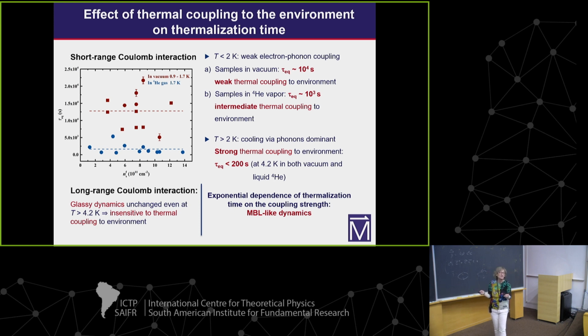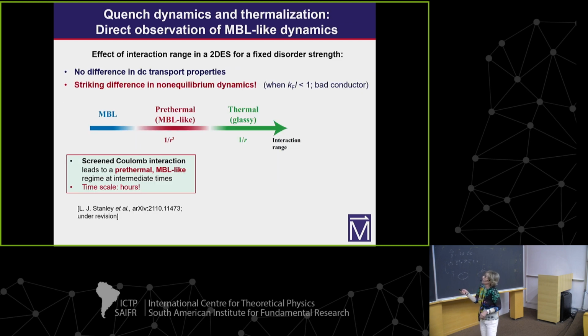In fact, it is this sensitivity to the coupling to the thermal bath that has been suggested to be used as a key experimental signature, or a way to distinguish between glassy and MBL-like dynamics. So this is what we have found: in the long-range case, the system thermalizes, but the dynamics is glassy because the system is frustrated. We have disorder, we have long-range Coulomb interaction. In the dipolar case, the dynamics seems to be consistent with pre-thermal MBL or MBL-like behavior.